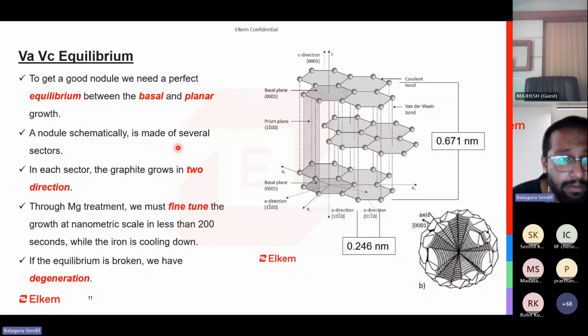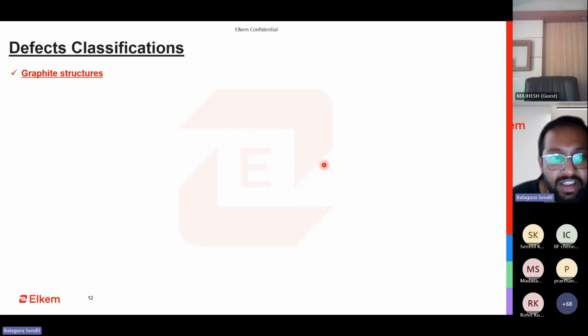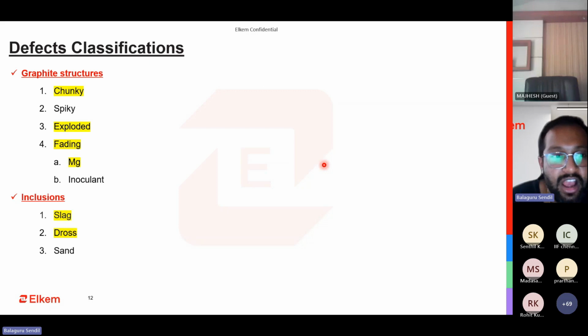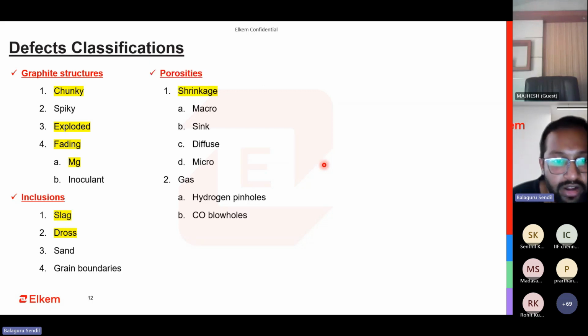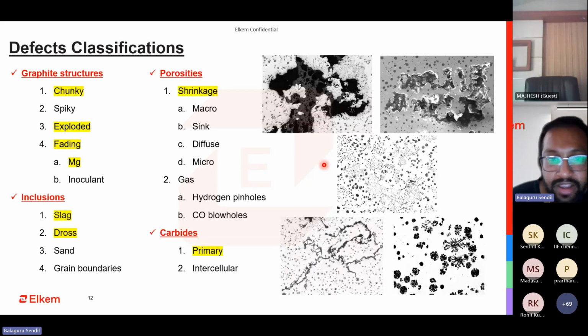Is this equilibrium, the VA and VC, the velocity that is growing in the A axis and the C axis? C is basically your planar and A is your basal. If this gets distorted, you get graphite degenerations, and you have seen many graphite degenerations here. I have just briefly put here the various types of defects that we have. What I have tried to highlight in yellow are the ones that can be related to your treatment process. If this gets disturbed, all these sorts of defects can come.